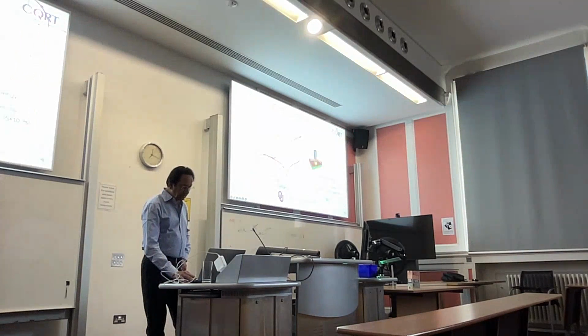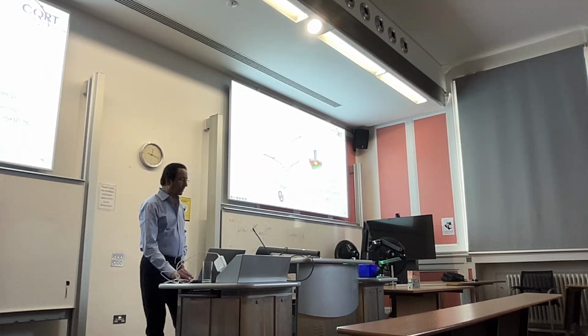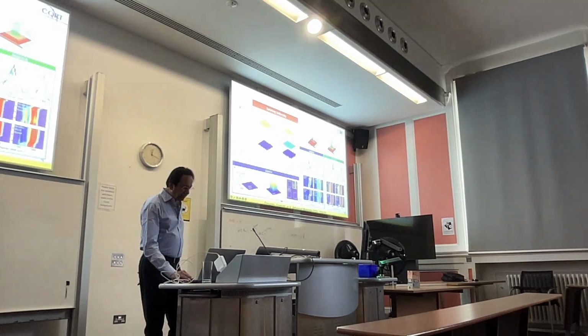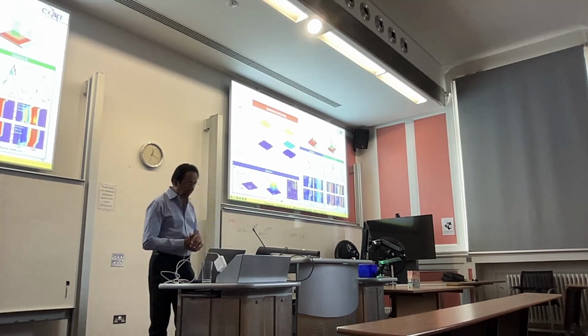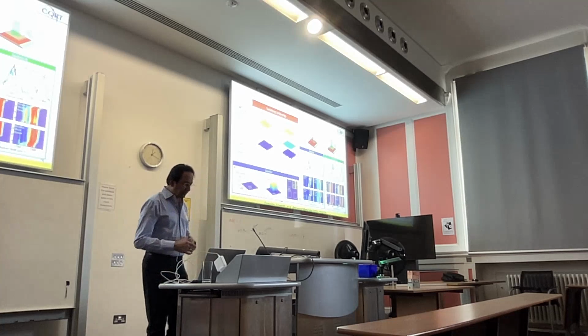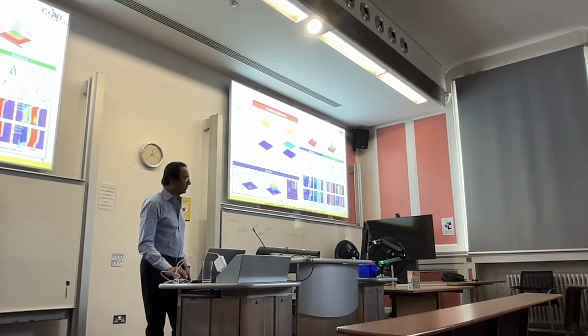Today we have made a device that switches with a switching voltage of about 70 millivolts. It's essentially 1 attojoule of switching energy, which is really, really small compared to most devices. And we can pattern this device down to almost 7 nanometers. The diameter of this molecule is about 1.5 nanometers, so I think realistically the smallest device we can build is maybe about 3 nanometers. This is what we think we can do.